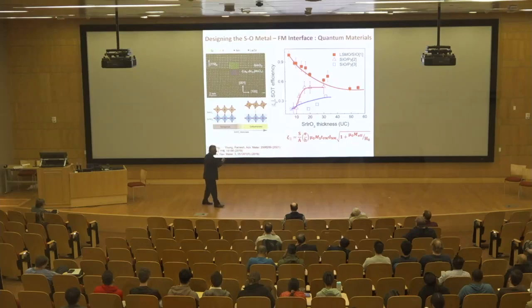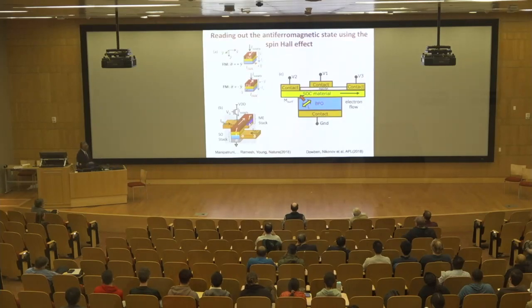So this epitaxial structure has given us a pathway to look at something very different. And so we said, okay, if that's the case, can we now go from this structure, which I showed you 10 minutes ago, where I have the full stack, the red layer is my ferromagnet, and I look at the ferromagnet magnetized this way versus this way, and read it out as a spin Hall current, going this way or this way. We said, what happens if I completely ditch the ferromagnet, and I put my spin orbit coupled material